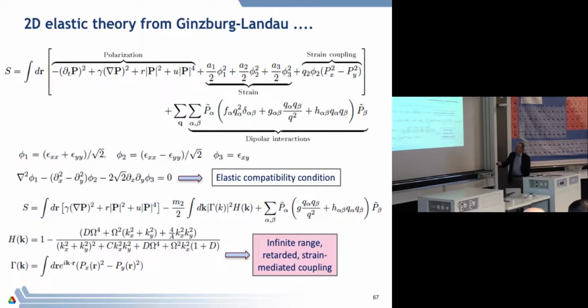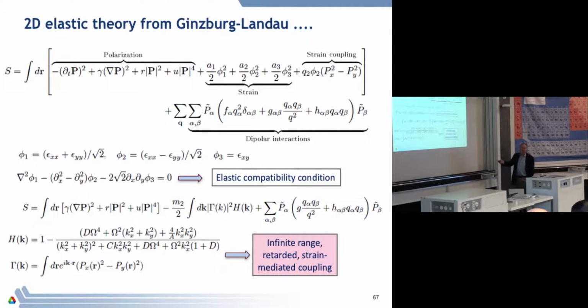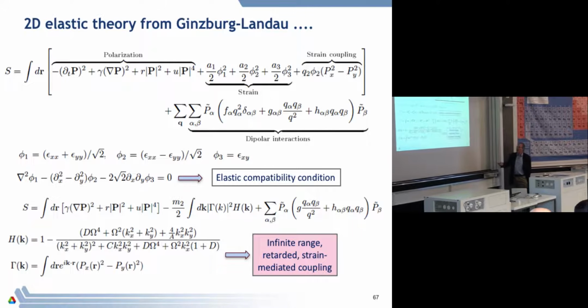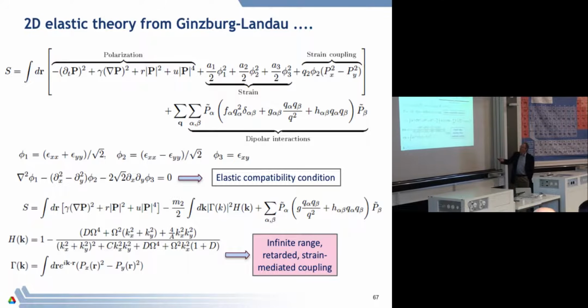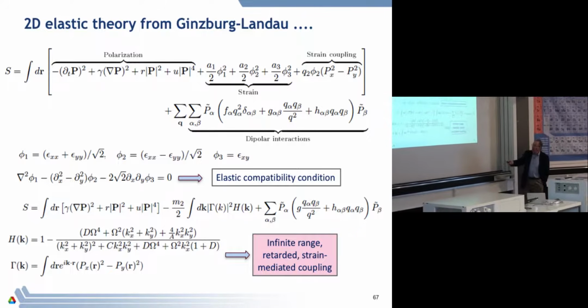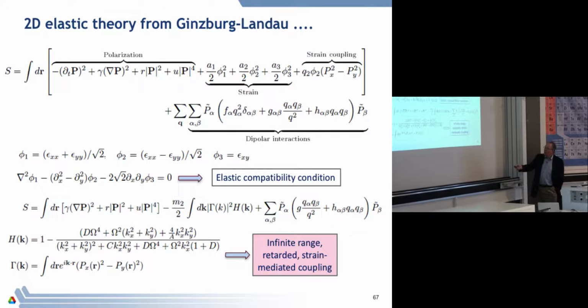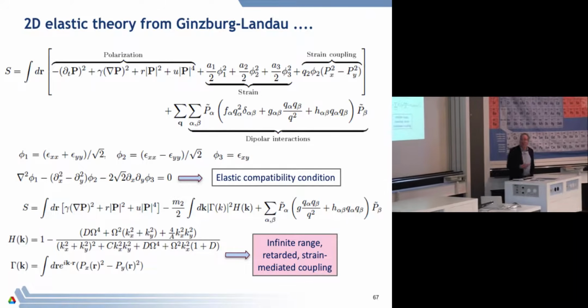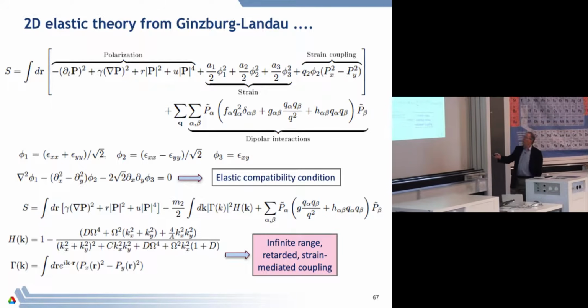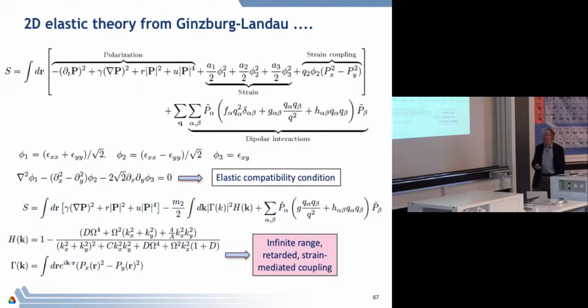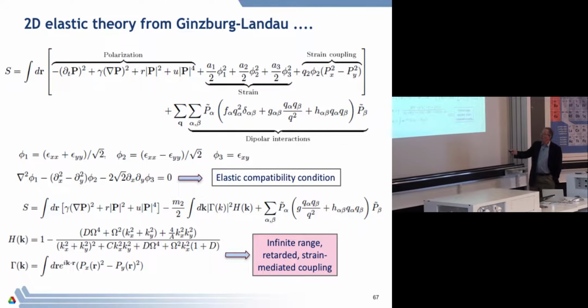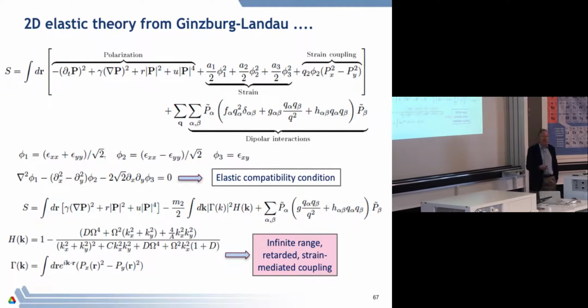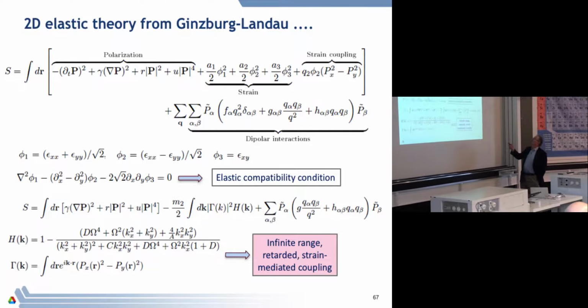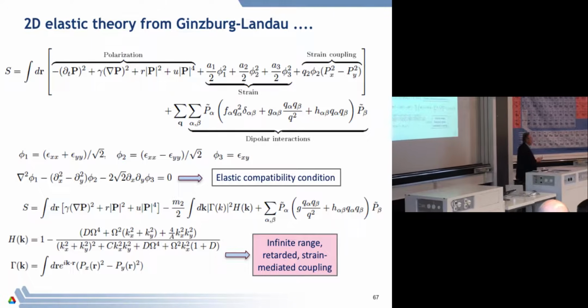But this is what that term looks like, and I have had to write it in k-space because that's the only sensible way to write this. And so here it is, it's a p fourth term, but it's coupling the Fourier transform of the polarizations to itself via a kernel. And that kernel depends, of course, on the wave vectors of the various components which are in here, and that's k, and it also depends on the frequencies of those components in here, because strain has a sound velocity and it moves at a finite rate.